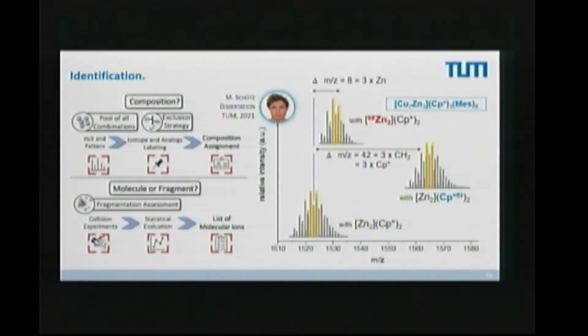And we label our hydrocarbons. Either we deuterate them or we put in a methyl group. If we do that, the unlabeled and the labeled will be differentiated by delta 14. And we have a differentiation here by delta 2. And with these two independent labelings, we can make 3 experiments. So the starting experiment without labeling, then the experiment with the 68Zn labeling, and then the experiment with the methyl labeling. And with doing that, we can see these shifts of masses. And by analyzing that with a fitting program, we can precisely assign formulas to each of the peaks in the mass spectrum, plus or minus 1 hydrogen atom, with a very high resolution up to the limit of our spectrometer.